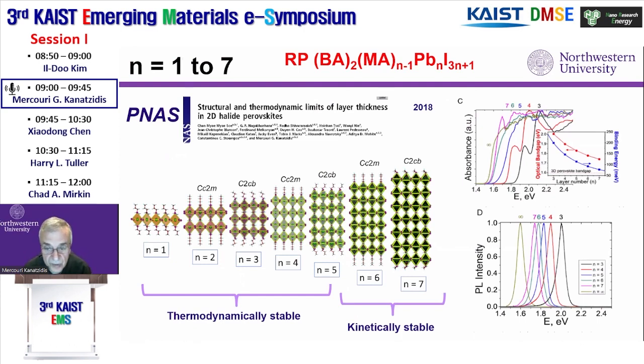And so here are the structures that we solved all the way to n=7. So these are crystal structures that are required to understand these at a fundamental level. And also the coordinates that are being generated are used throughout the world by theory groups who need the coordinates to do the proper modeling. They don't have to guess what the structure is. And all the way to 7, you can see here, for example, the photoluminescence spectra in the lower right. You see the maxima are very regular, and everything is where it's supposed to be. So as the band gap gets smaller, the PL moves to the red, and the same for the absorption.